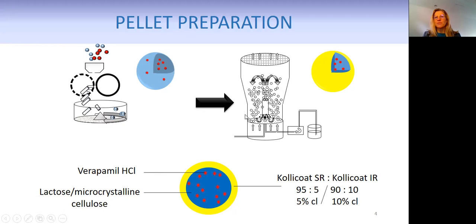So the pellet cores move up in the fluid air stream, and a spray nozzle applies the polymer dispersion continuously on the pellets. For the polymer dispersion, we actually used a polymer blend. We used a mixture of polyvinyl acetate, which is insoluble in water, Kollicoat SR, and Kollicoat IR, which is a polyvinyl alcohol polyethylene glycol graft copolymer, which is a soluble polymer. So by mixing these two, we can adjust the permeability of the film coating.